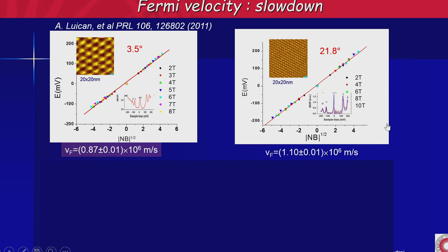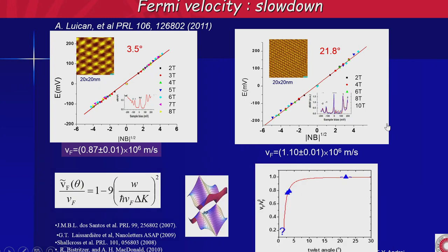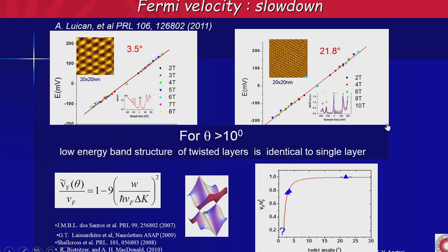Another thing that happens when you get to smaller angles, because the bands become flatter, is that your Fermi velocity is renormalized. It becomes smaller, and we actually measured the Fermi velocity as a function of angle using Landau level spectroscopy, and we found these points. Theoretically, it should go like this. So you see that when you go to a very small angle, the whole thing stops. You have a completely flat band. Your quasi-particles don't move anymore. At the time when we did this, we had no idea what was going to happen here. In some sense, it has to be singular, because at some point it becomes a bilayer, and you have a totally different band structure. However, when you're at more than 10 degrees, you recover the single-layer graphene band structure, and we use that in order to screen the random potential in the substrate. So we use two layers at a large angle, and that gives you a much cleaner